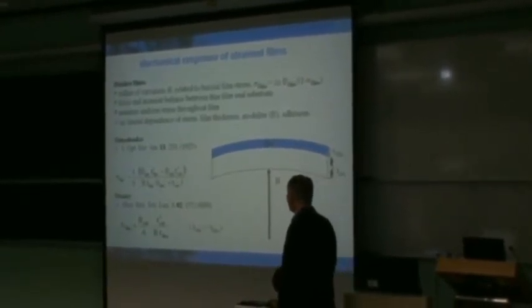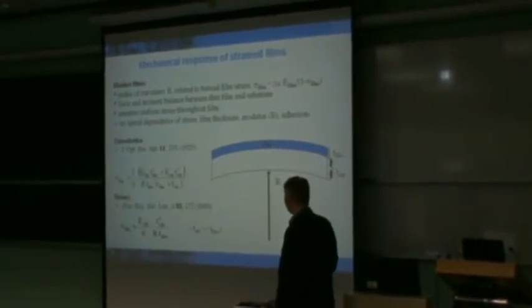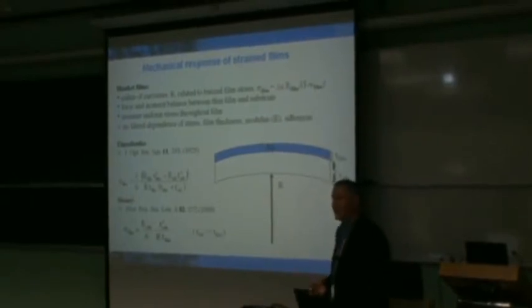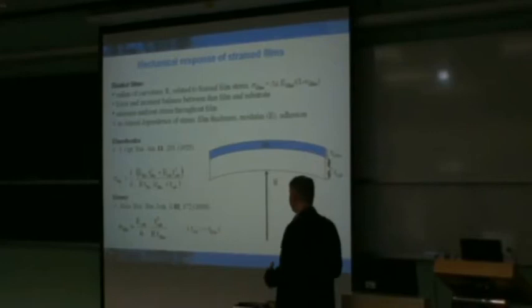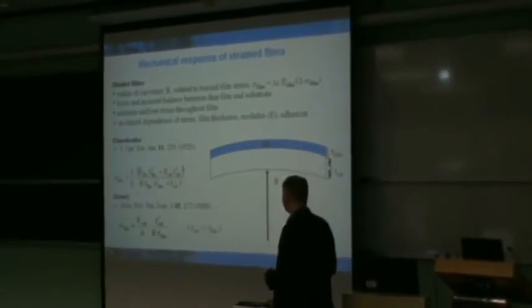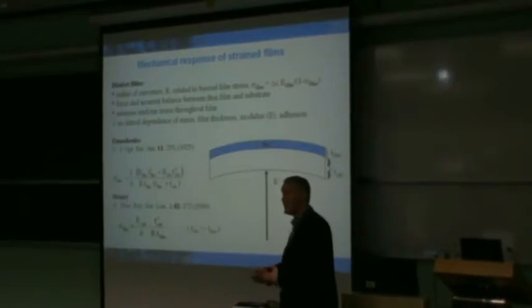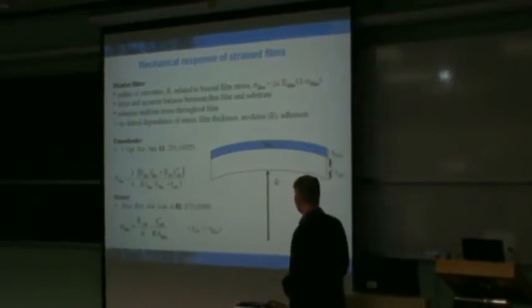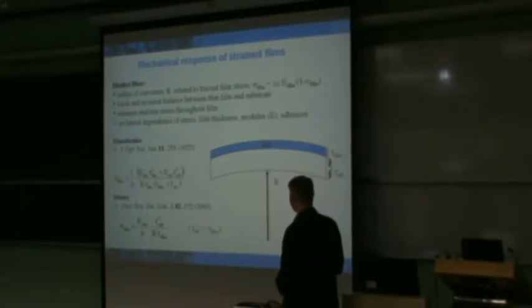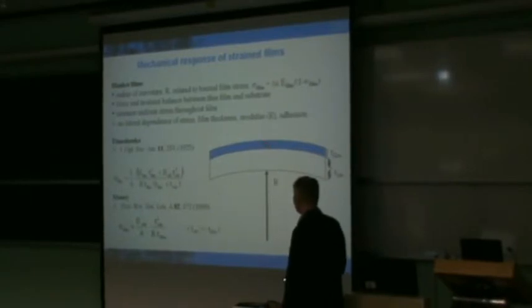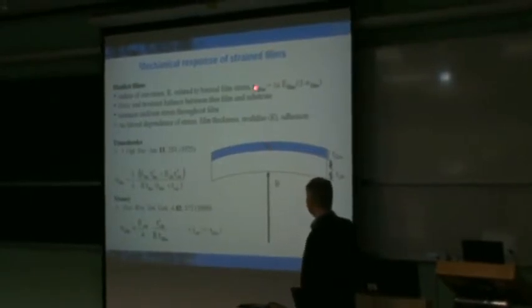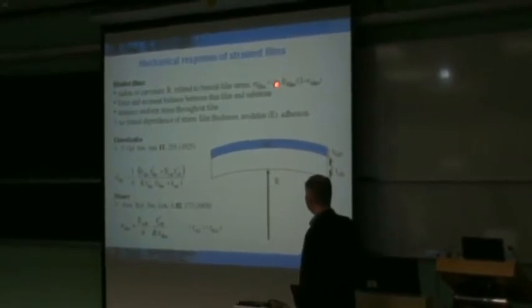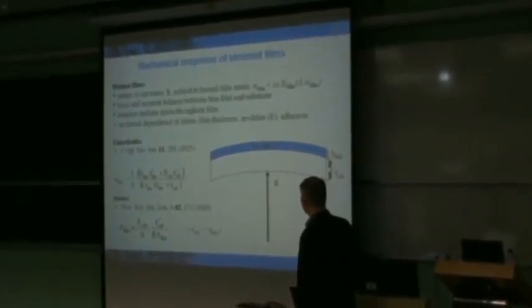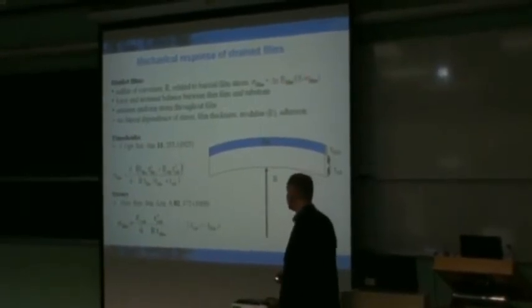Nevertheless, that can be used to help quantify the stress that exists here. What I start with showing here is delta epsilon, and that refers to a quantity called the eigenstrain. And that will help delineate the fact that there is a difference between the equilibrium state of that film and the substrate on which it resides that helps drive this change that leads to this elastic relaxation. And you can see right here, assuming a biaxial stress state, isotropic biaxial stress state, in the film, that you can relate that stress to the elastic constants of the film, both the Young's modulus as well as the Poisson ratio.